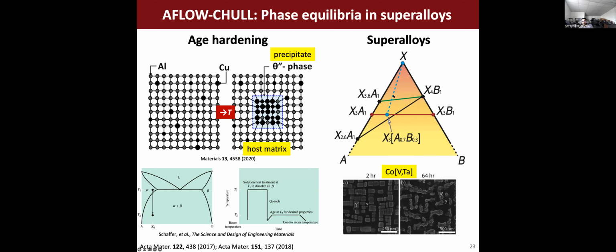However, if the topology of the convex hull is such that I actually have a tie line here, you can see that there exist no compositions where there's going to be a tie line that connects between the red and this top line. So this is a way of screening compositions of interest for the superalloys. We did this analysis in 2017, as part of our way of screening through different superalloys, and we made a number of predictions. And in 2018, an experimental group independently verified some of our predictions.